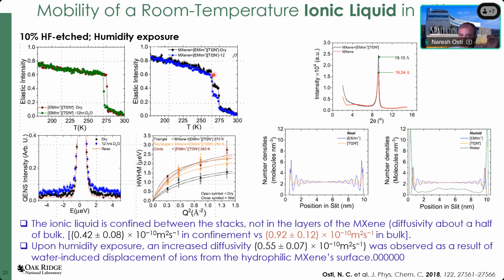We stayed at somewhere here in this temperature and collected the quasi-elastic neutron scattering signal, extracted the width parameter of the signal, and plotted it as a function of the square of the momentum transfer vector, from which we extracted the diffusion coefficient. The diffusion coefficient we found for this confined ionic liquid is 0.42 compared to the bulk value of 0.92. This is roughly half. If you recall, the water diffusion coefficient that we found for the metal ion intercalated in the pristine MXene case was also half of the bulk value. This gave us an idea that maybe in this system also, the ionic liquid is not between the layers, because the decrease in diffusivity is just by half.